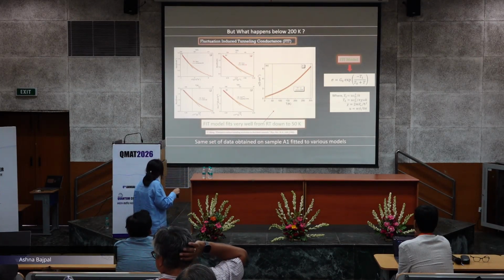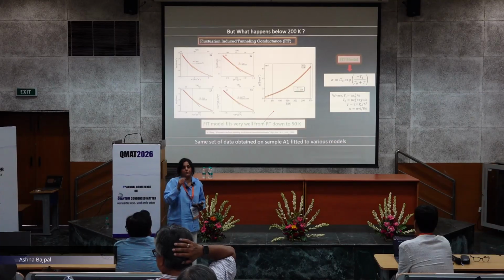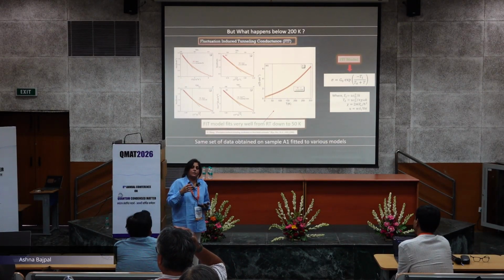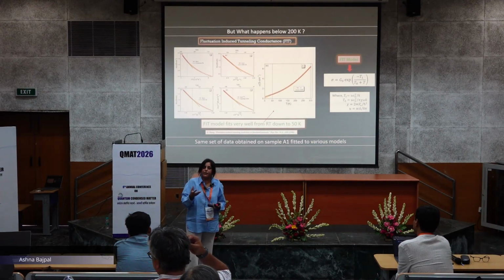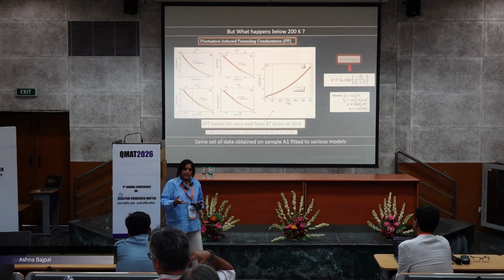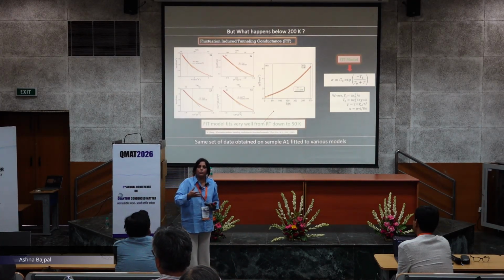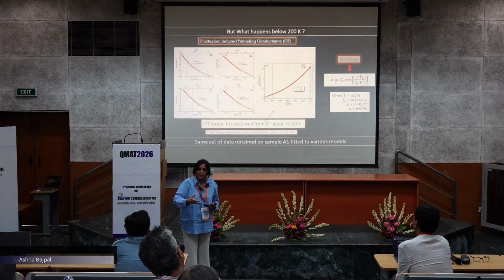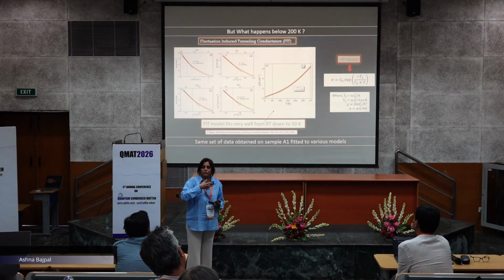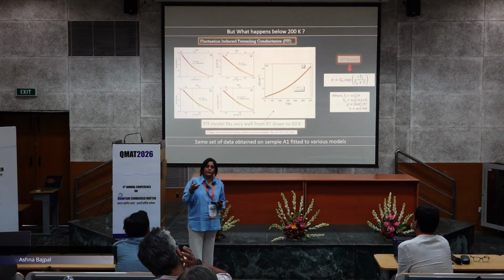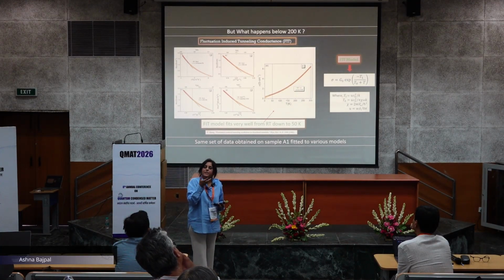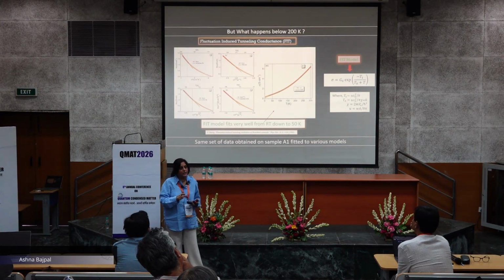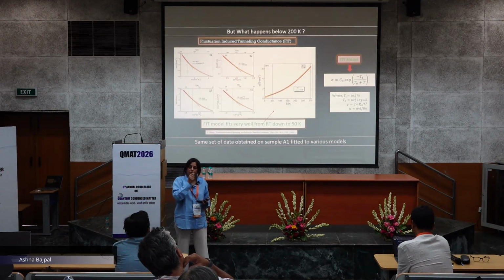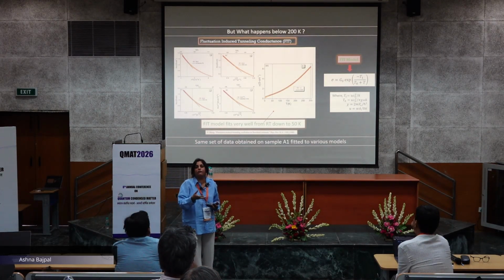So now we focus on one sample. As I said, we synthesized samples because we suspected that disorder is playing a part. So we synthesized samples with various grain size variation, grain boundary density variation, Ru rich, Ru poor, and such kinds of things. Nevertheless, the result was still the same. So we focused on one sample which was morphology-wise very similar to the one reported by Hille, who synthesized this compound for the first time.